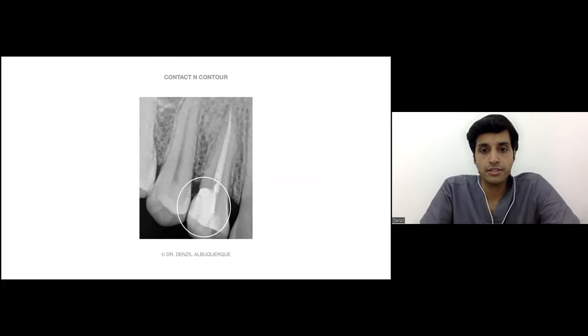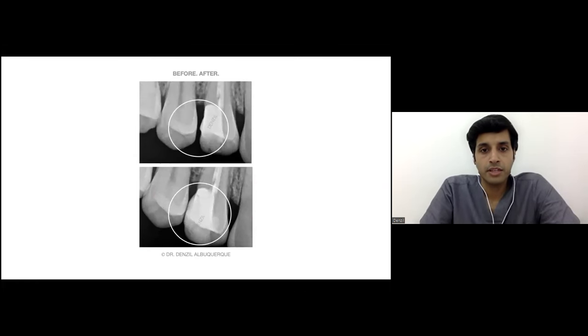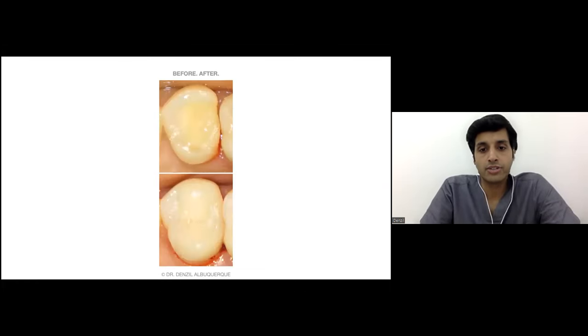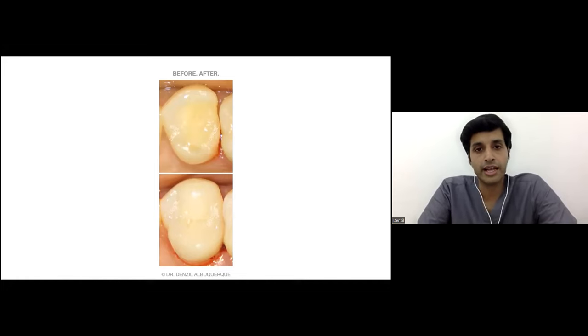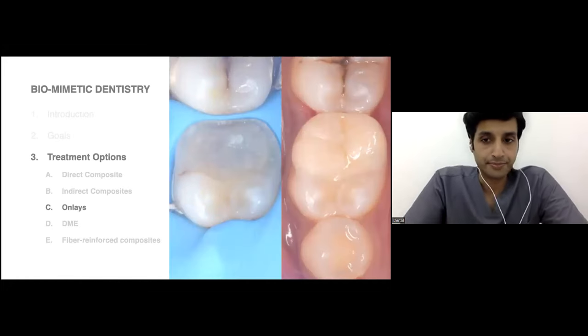Here you can see the before and after. So these are indirect composites, and there is no force acting on the tooth. The C factor is reduced because only the resin is bonding, the cementing medium, which in this case was dual cure resin. You can use dual cure resin, you can use flowable, you can use composites themselves, which are heated composites. Any of these can be used for cementation.